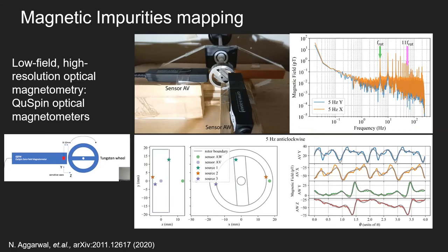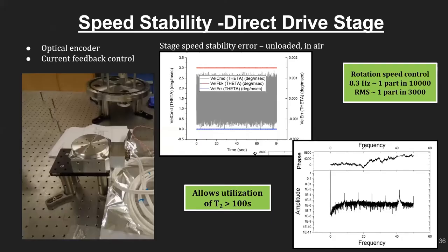We've studied the spectrum of the magnetic field from the rotating tungsten wheel and been able to identify the presence of a few discrete magnetic impurities, none of which are at a level sufficiently concerning to limit the sensitivity of the experiment, in the limit that the shielding factor is as good as we are designing it to be. So we're fairly confident at least that the specs on the rotor will be sufficient to reach the first round design sensitivity.